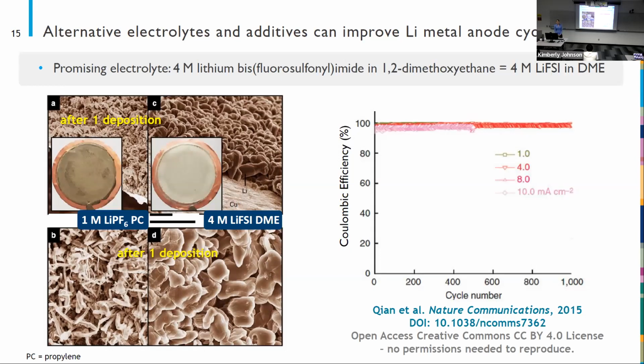So there's a lot of strategies for improving lithium metal anodes. One of the most common ones that people try and work on is to replace the electrolyte. The electrolytes that are used in your lithium ion batteries do not cycle lithium metal very well. And so we try and replace the electrolytes with things that are more favorable for lithium metal plating. One of those electrolytes is 4 molar lithium bisfluorosulfonylimide in 1,2-dimethoxyethane. And this is a mouthful to say, so we just call it 4 molar lithium FSI and DME.